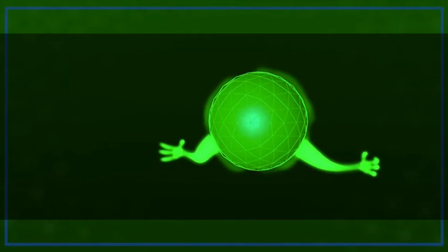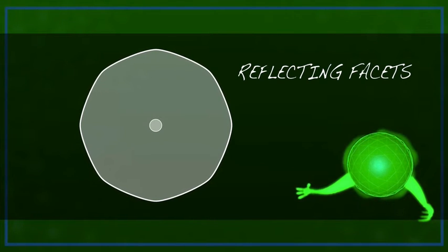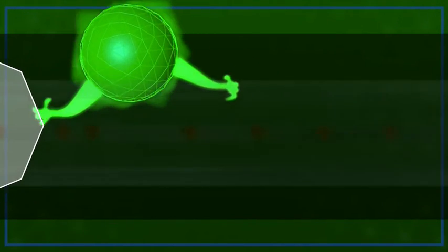Once the laser is assembled as before and we apply pump power to the diodes, we quickly see that much of the pump light simply passes down the cladding without intersecting successfully with a dopant ion in the core. Without this intersection and transfer of power, the laser cannot work. The solution to this problem is to create extra reflecting facets on the outside of the first cladding. Snitzer, remember him? Found that changing the shape causes enough redistribution of the light in the cladding to force a high level of interaction with the core.